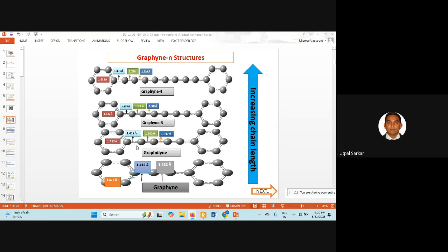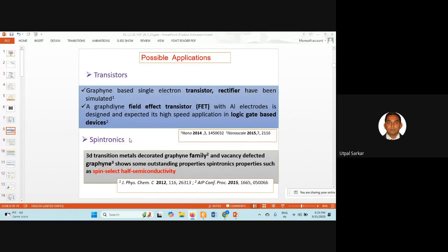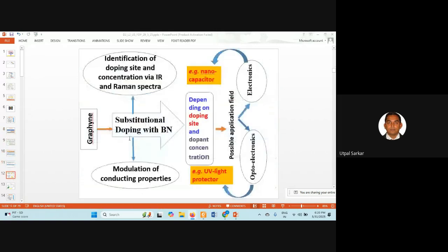Okay, similarly, if you increase the number of acetylene linkages, some shrinkage of the bonds and some expansion of the bonds are occurring, and you are getting different types of bonding, so the nature of bonding can change. That means hybridization is also changing, and that gives rise to different conductivity or semiconducting band gap.